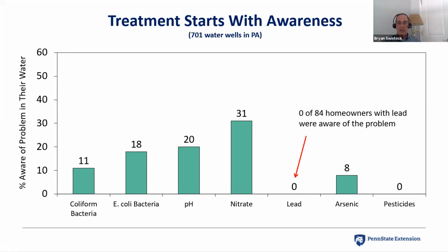In this particular case, out of the 701 water wells, 84 had lead above the action level. And when we went back to those 84 homeowners and looked at their surveys, 0 out of those 84 people selected lead as a pre-existing problem that they knew they had. So there was total lack of awareness of lead, which is not terribly surprising. It has no obvious symptoms other than the copper symptoms that you might notice. And it's not tested that frequently. At least it hasn't traditionally been tested very frequently compared to things like nitrate on this list, where there's more awareness because there's more testing.